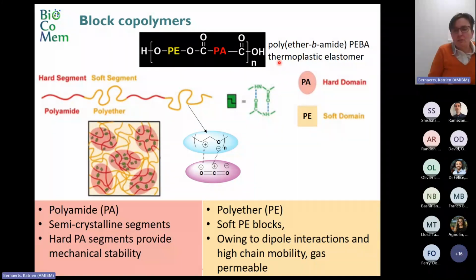And the PEBAs belong to the class of the thermoplastic elastomers. Thermoplastic elastomers are characterized by hard and soft segments, and in our case, the polyamide is the hard segment and the polyether the soft segment. And those hard segments arrange because there is hydrogen bonding between the amide bonds, and this gives you the mechanical strength of the membrane. On the other hand, you have the soft segments that, as already explained, thanks to the dipole interactions and the chain mobility, are responsible for the gas separation. Typically, the polyamide segments are semi-crystalline.